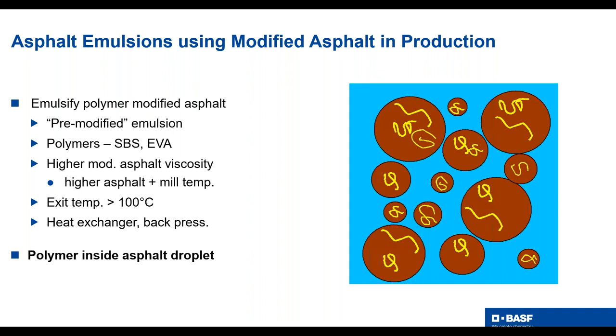modified asphalt that you're making emulsion from, usually those will be run at a little higher asphalt temperature. And so the emulsion temperature will have to be a little higher. Sometimes the exit temperature will be above 100 degrees C. You actually have to have a heat exchanger to cool that down so it won't boil coming out of the mill.